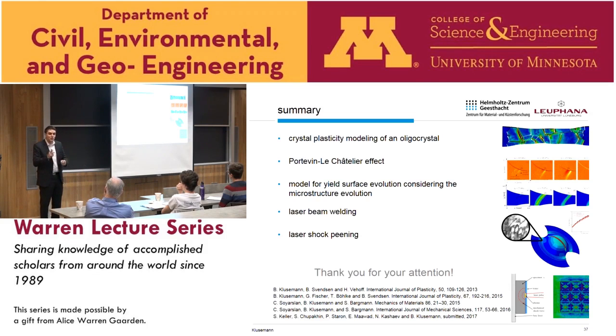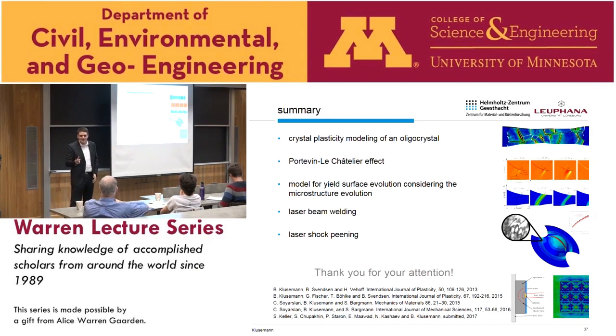On the contrary, we didn't go deeper at that stage because our first results showed perfect agreement, which we didn't expect. We were expecting there had to be some large differences. I showed you the ideal plasticity, obviously, and this was also a check for us to see, is this really true what we're getting out here? It was the same for us. We were also surprised that we could already accurately predict the deformation and also the orientation gradient field in this way without any sophisticated model.